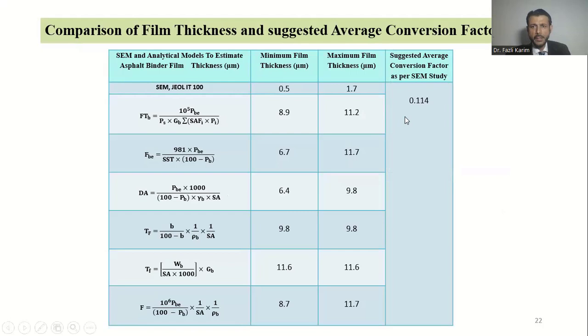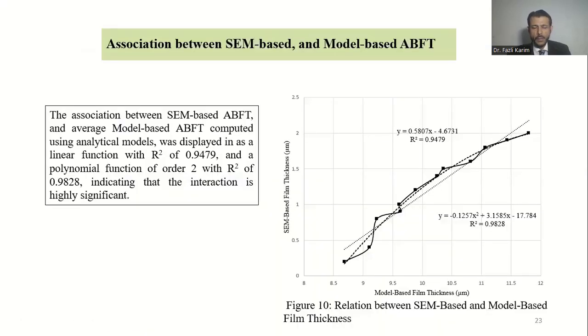Now, this is another transformation factor developed for the recycled mixture, so that the values of film thickness based on analytical models can be transformed into the value of film thickness based on scanning electron microscope. The association between SEM-based asphalt binder film thickness and average model-based asphalt binder film thickness computed using the analytical model was displayed as a linear function with R square of 0.947 and a polynomial function of order 2 having R square of 0.982.